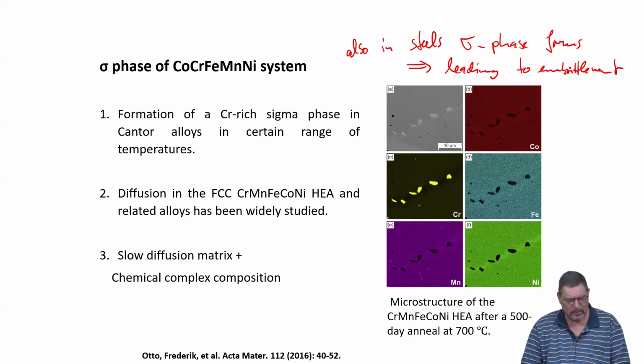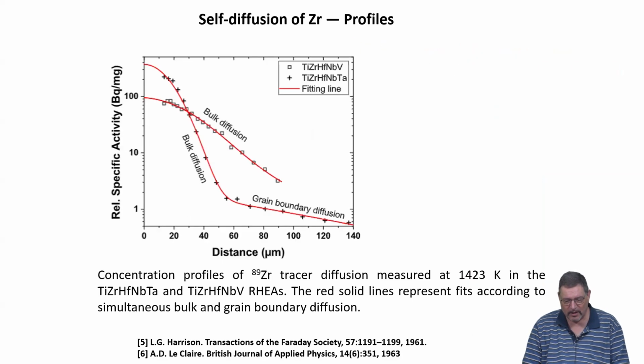However, in this case, it's nice because at the very fine scale, the sigma phase can really provide a hardening phase, while the majority is still FCC, so you can get precipitation hardening very efficiently from that phase. And in this case, it can also be thought of as a high entropy intermetallic, because it consists of also the ingredients of the Cantor alloy. And so we will also talk about how the diffusion in this intermetallic compound phase, when it's having many different constituents, will take place. So if we now go to the first part, diffusion in the titanium, zirconium, hafnium, niobium, tantalum, we compare it to a variant where we replace the tantalum with vanadium.